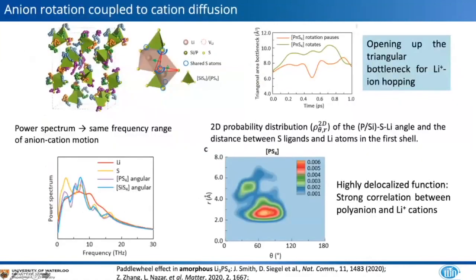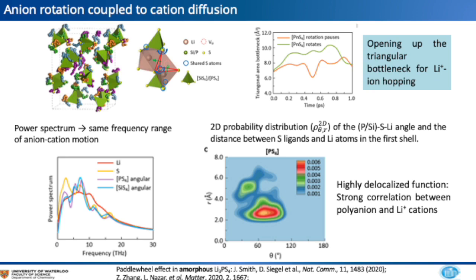So it is a similar effect to what I just described with the sodium. We again have a transient opening up of this triangular window, which is where the lithium ions pass in this structure. And so when we pause the rotation, the window disappears or diminishes. When we let the polyanion rotate, this is through AIMD calculations, the window opens up. And this is what lowers the activation energy barrier. And we notice in the power spectrum that we see the same frequency range for the rotation of the polyanion groups as we see for the lithium in the material. So that again is evidence for the coupled mobility.